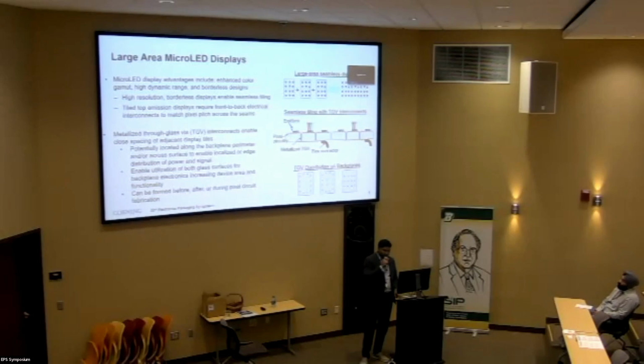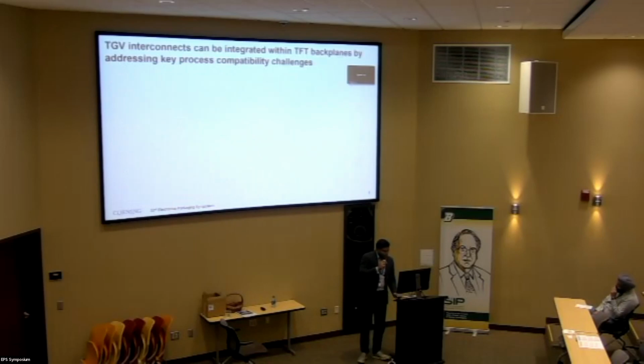One advantage with incorporating through glass vias in the backplane is you don't need to route the signals planarly, through the surface. You can do it through the vias now. So it frees up a lot of the real estate on the backplane, so you can include more device functionalities within that. And these through glass vias can be formed before, after, or during pixel circuit fabrication.